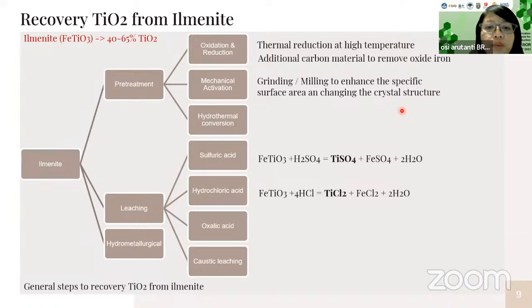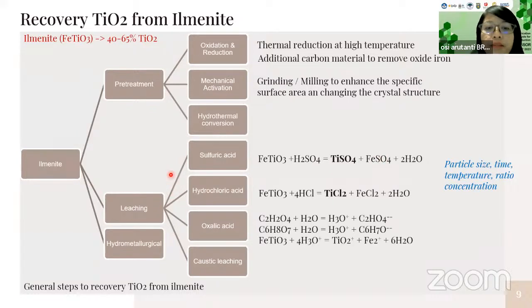And for the leaching process, sulfuric acid and hydrochloric acid can be used. Okay. And the optimum condition depends on the particle size of ilmenite, the time and temperature for the leaching process, and the concentration ratio between the acid and the ilmenite. This is leaching by oxalic acid, and the third one is hydrometallurgical by caustic leaching.